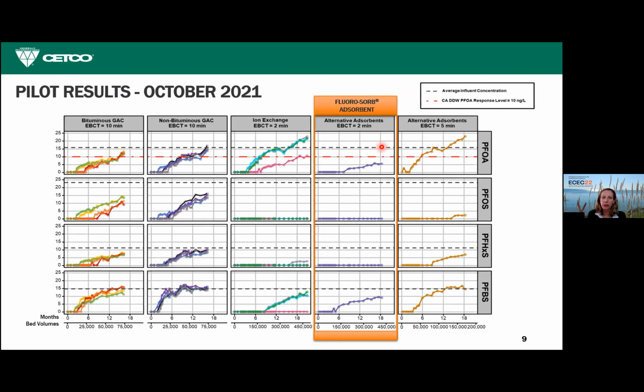And the Fluorosorb results are shown here, highlighted in orange. For PFOA, right here at the top, Fluorosorb lasted the longest. The way you read this is that the concentration is on the y-axis and time to breakthrough is on the x-axis. The longer time to breakthrough means more water was treated before you hit your treatment target, which in this case is the California notification level of 10 nanograms per liter for PFOA. You can see that all the other media broke through to that red line prior to Fluorosorb, and that was for PFOA. For PFBS, this pink one here is the best performer, and that's ion exchange resin PSR2+.